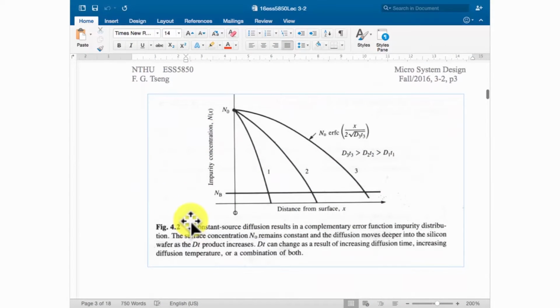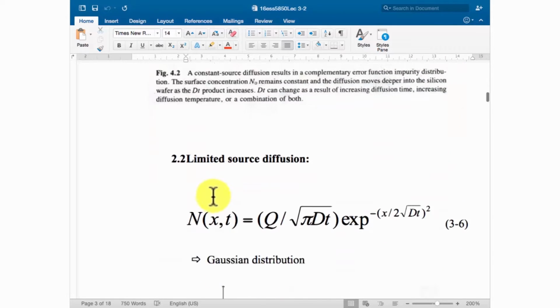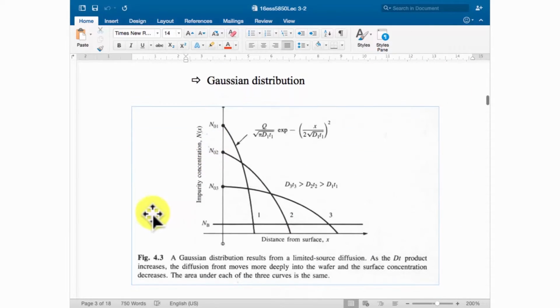Actually, all the fabrication processes will go through these two processes. So we use the first process to introduce a certain amount of impurity we want. After that, we bring the substrate into a furnace without any source, and just elevate the temperature for the annealing process, to distribute the impurity into the profile we want. So a two-step process is usually used for diffusion.